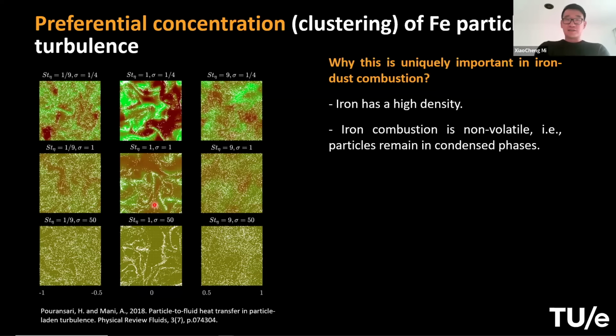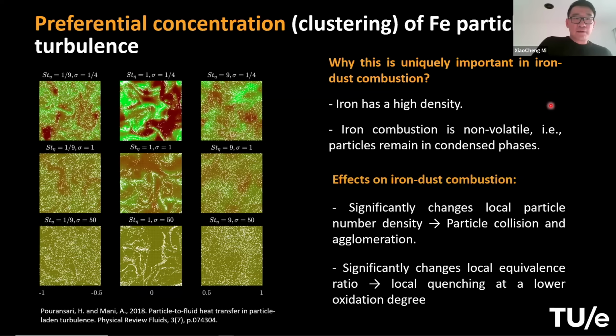And this is uniquely important for iron dust combustion. The first reason is iron has a high density, so for the same size, it has a higher mass and higher inertia, right? And the second one, as I mentioned before, is that iron combustion is non-volatile. That means over the whole course of its combustion, it remains in the condensed phase. It's not like coal or biomass or other volatile solid fuels, which may initially be influenced by such a phenomenon, but most of the heat release comes from gas phase reaction, which is no longer affected by preferential concentration. So this preferential concentration may have certain effects on iron particle combustion.